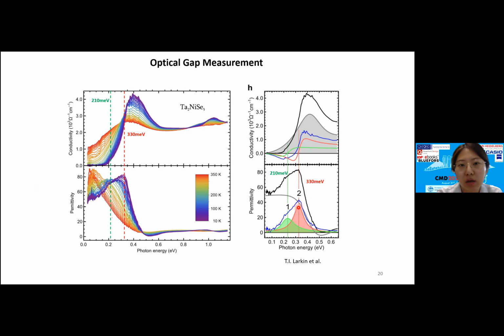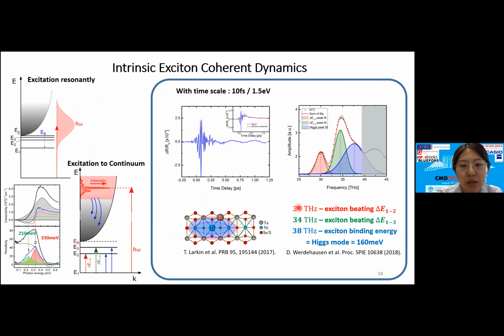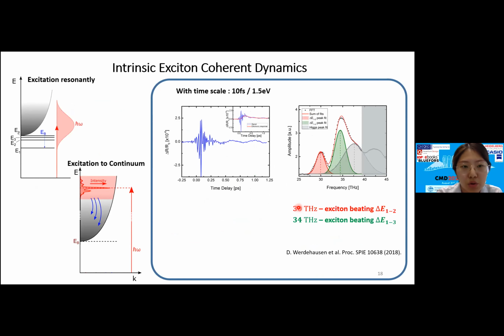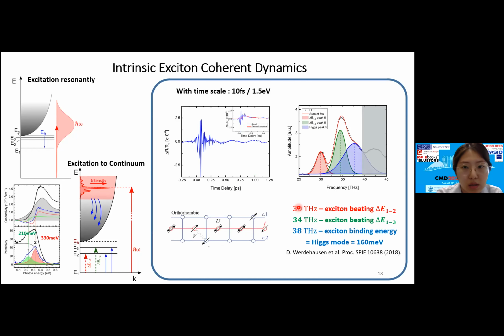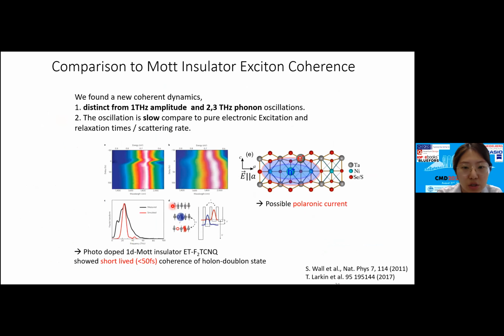Firstly, they suggested this, and why we suspect this is the polaronic current is because, in principle, this excitonic energy is very fast, like in this Mott insulator. It should oscillate very fast, in a few tens of femtoseconds or so. We cannot directly compare to this paper, but in our measurements we also expect very fast oscillatory behavior, yet we get a picosecond coherent current, so we can suspect there is a polaronic effect.